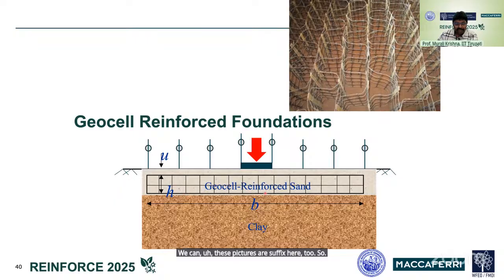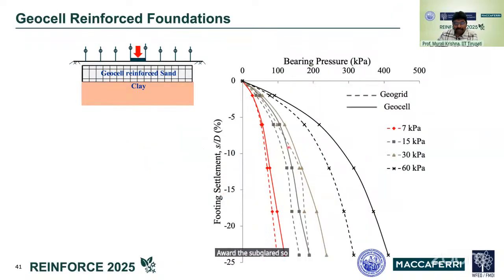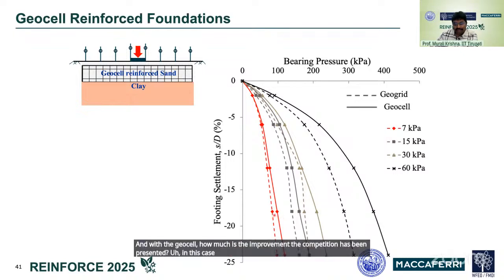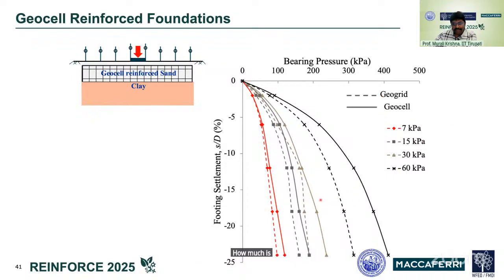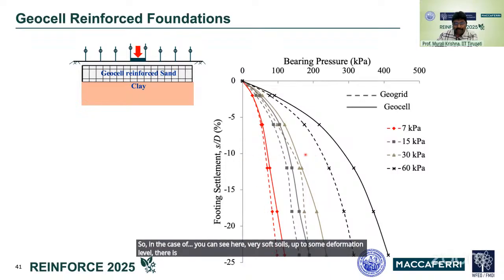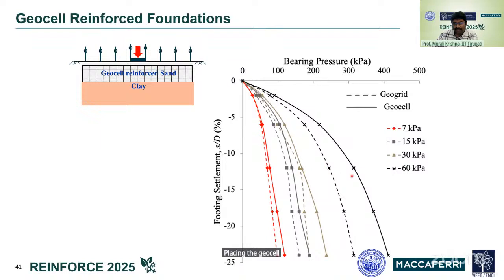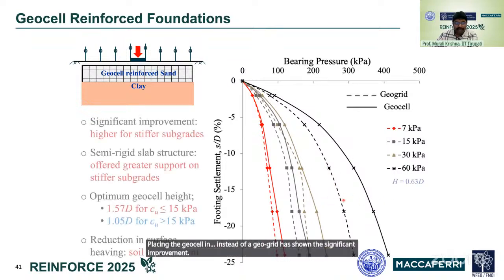So the next configuration is the geocell reinforced sand over the subgrade soil. Here, the difference with the geogrid and how much improvement there is with the geocell, the comparison has been presented. In this case, it's not the unreinforced material, but with geogrid and geocell, how much difference there is has been depicted. In the case of very soft soils, up to some deformation level, there is not much difference between the geogrid and geocell. Whereas if you see the 60 kilopascal very stiff soil, placing the geocell instead of a geogrid has shown a significant improvement in the capacity.